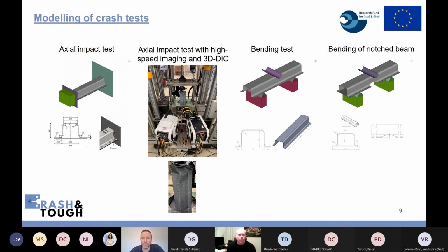So the next step is modeling, and in this case validation of the simulations we have been performing. First we have axial impact tests performed by Voestalpine, and we have run similar tests at LTU, but in this case we have added 2 high-speed cameras and put some speckles on the crash boxes, in order to measure the deformation during the compression. We also measure the load versus intrusion, and we could also detect when potential cracks occur and how they propagate. Then we have the bending tests shown by Pascal. LTU has been running the bending test without notch, and Ricardo will show the one with a notched beam.